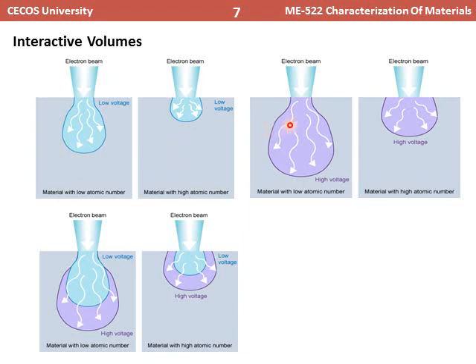However, if we increase the accelerating voltage, then the depth of penetration will be much larger in the case of low atomic mass number, and similarly the depth of penetration will also increase in the case of high atomic mass number, because you are increasing the accelerating voltage. If we sum up both things in the diagram, you can easily see that by increasing accelerating voltage, the depth of penetration will increase in low atomic mass number as well as high atomic mass number.